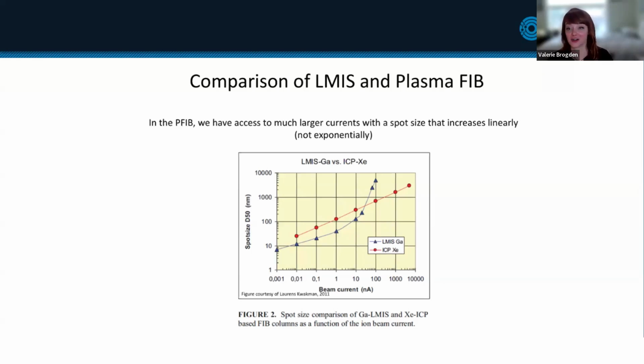So PFIB really shines on hard materials, right? Because you have access to much larger beam currents. But with mixed mechanical systems, you have to be a lot more intentional. The reason is that mixed materials are going to have different sputter rates. A softer material is going to sputter at a different rate than a harder material. And what that's going to result in is an artifact called a curtaining feature. It's a streak down the middle of your cut face where it milled a little bit faster or a little bit slower. And especially if you're using high current, it's really going to amplify those curtaining artifacts at the interfaces between materials with different hardnesses or densities or porosities.